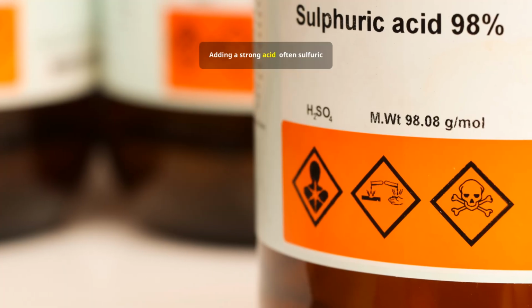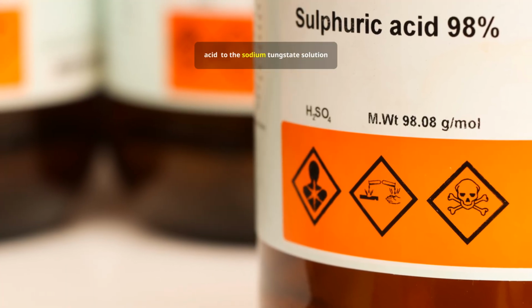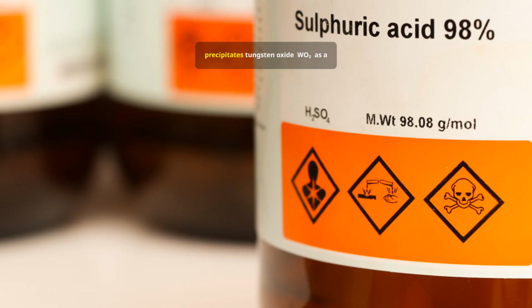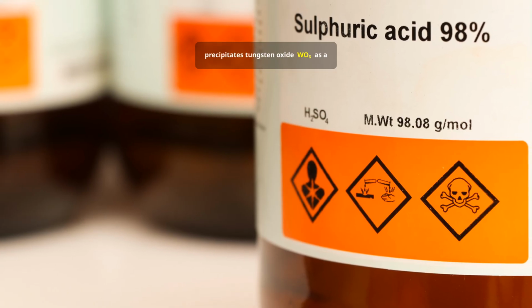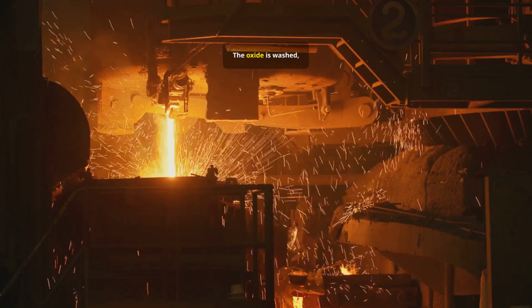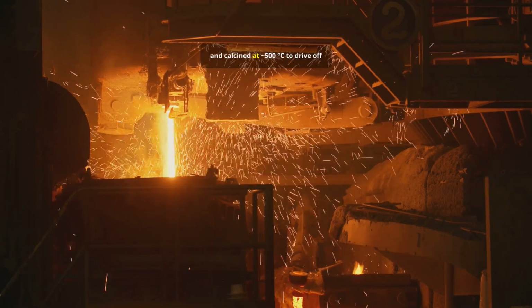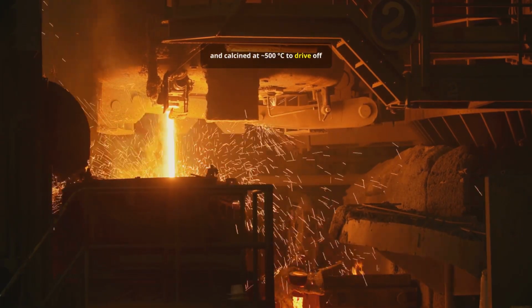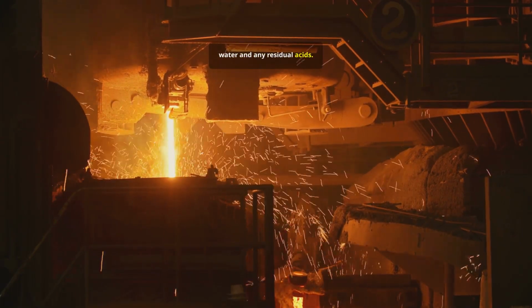Adding a strong acid, often sulfuric acid, to the sodium tungstate solution precipitates tungsten oxide, WO3, as a yellow powder. The oxide is washed, dried and calcined at 500 degrees to drive off water and any residual acids.